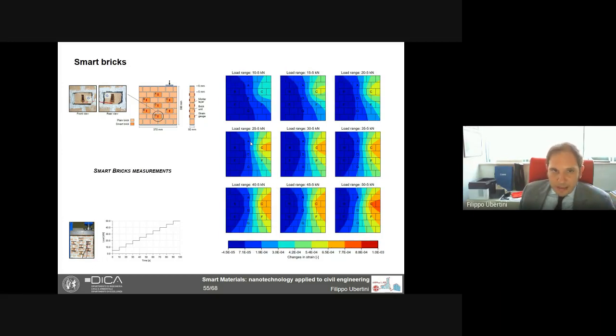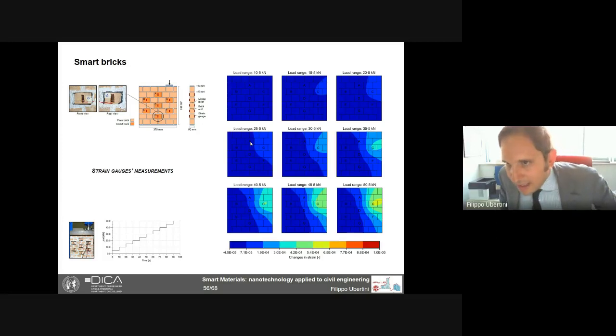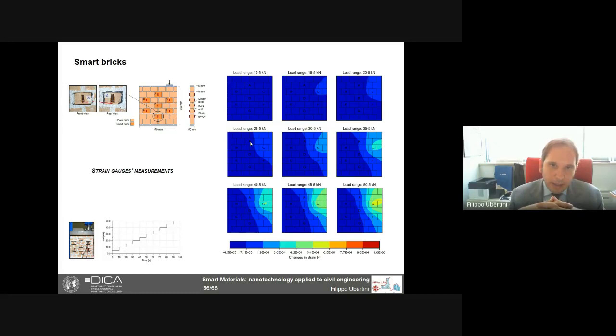If we do the same with the strain gauges that are attached on the smart bricks, we get maps that do not really make much sense. The strain is much more localized than in reality, let's say if we take the finite element simulation as a replica of the reality, which is due to the fact that the strain gauges are very local in the measurement they provide.